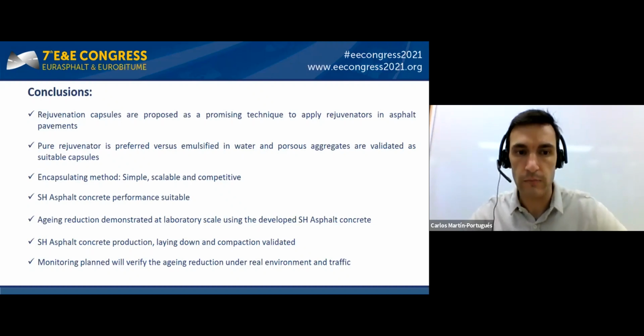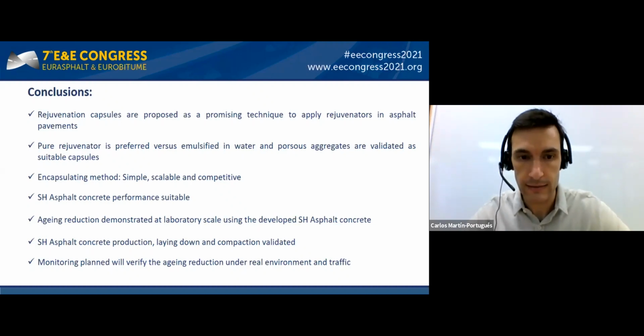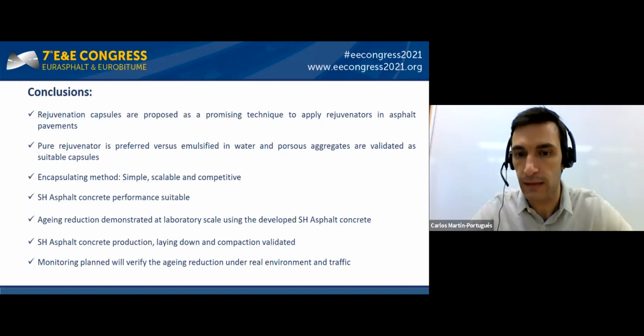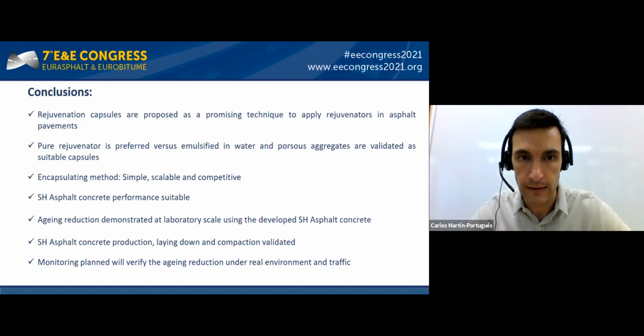The aging reduction was demonstrated at laboratory scale, as Francisco described. And the self-healing asphalt concrete production was normal, as well as the laying down and compaction that was validated. We will monitor the road and we will verify that the aging reduction is as expected in the real environment and real traffic. So thanks for attending. And if you have any comment or question, we will be happy to answer, as you have our contact details.